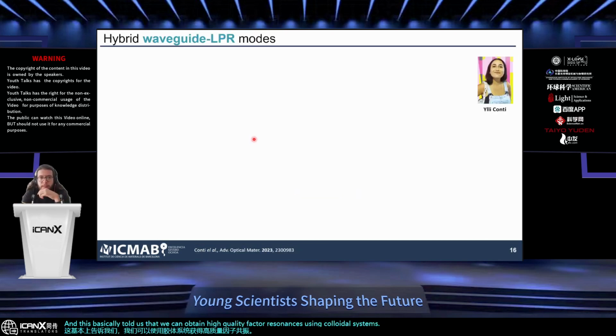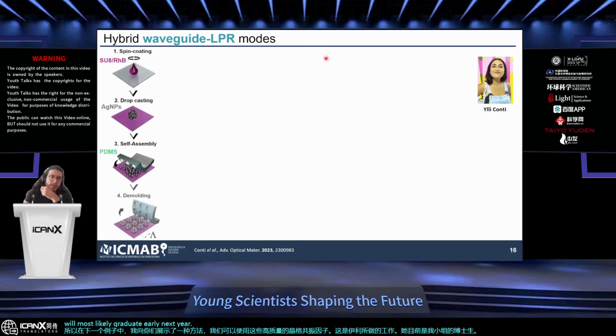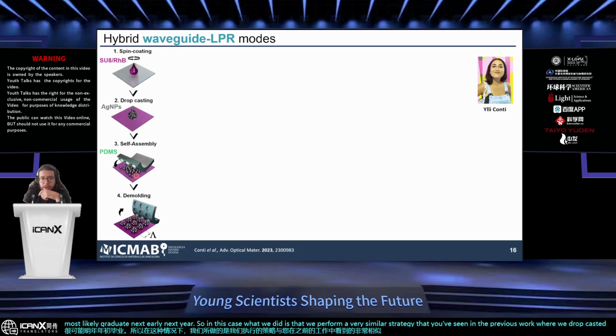And so in the next example, I will show you one way that we could use those high quality factor lattice resonances. And this is work done by Yili. She's currently a PhD student in my group. She will most likely graduate early next year. So in this case, we performed a very similar strategy to what you've seen in the previous work, where we drop cast a nanoparticle solution and dry it under a mold. But in this case, before performing the self-assembly, we spin coated a photoresist layer containing a dye.